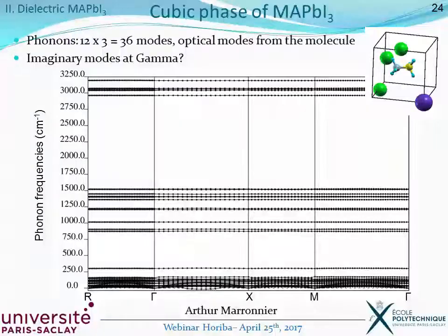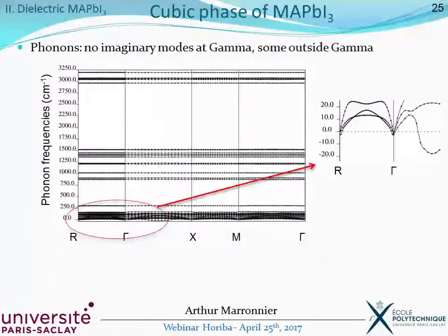Again, just to show you one result of phonons, as you can see, the results are totally different from the cesium case. You have many more modes, as you have many more atoms in the structure MAPbI3. MA stands for methylammonium, so many atoms. And one other big difference is that you can see here lots of high frequency optical modes, which are actually the signature of the organic molecule inside the inorganic cage. And you would ask me if, again, we have negative modes around gamma. Well, you can see here on the zoom that we don't have any negative modes at gamma. We don't have the same structural instability. This negative mode here on the right is just due to temperature.